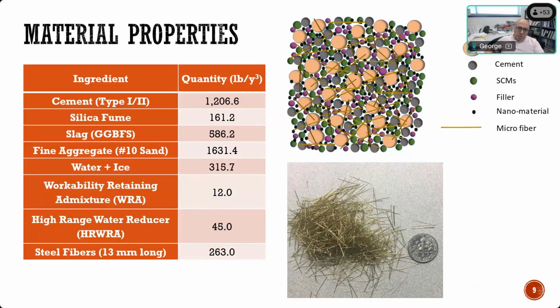So to present a little bit more information about what are the constituents or ingredients of UHPC, this is a mix that was developed 6 years ago using local material in Nebraska, and that's the composition, and that's a schematic presentation showing the particle sizes. So the largest particle size is the fine aggregate. You have a fine aggregate number 10 sand, that's the majority of the mix. Comes after that the cementitious material, which is cement, and it has slag and silica fume as supplementary cementitious materials.